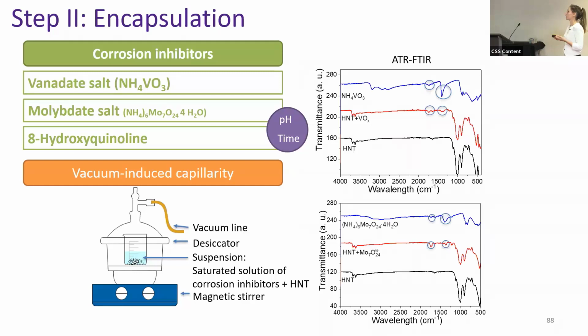To check if the nanotubes were indeed loaded, we characterized them by infrared spectroscopy, and we can see in this spectra here, at the bottom in black, the spectra of the empty nanotubes, at the top, the spectra of the inhibitor, and in the middle, the spectra of the nanotube loaded with corrosion inhibitors, where we can see characteristic peaks of the inhibitors in the spectra, the same with the molybdate. And this is evidence that the nanotubes were indeed loaded.